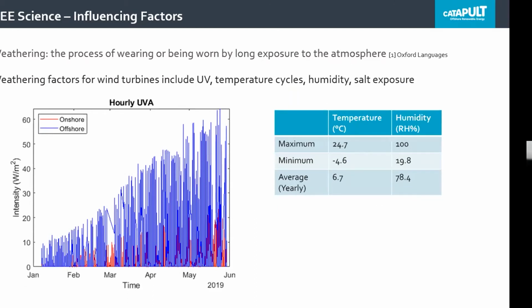Weathering, I think, is one of the key critical material parameters that would be taken into consideration in terms of evaluation of new solutions. So currently, what you can see on the left is the UVA intensity measured onshore and offshore, and these two sites are about 8 miles apart. One's 3 kilometers offshore and the other one is just onshore. And you can see that the UVA intensity is 2 to 3 times as high